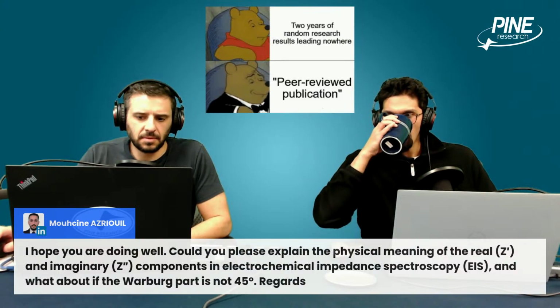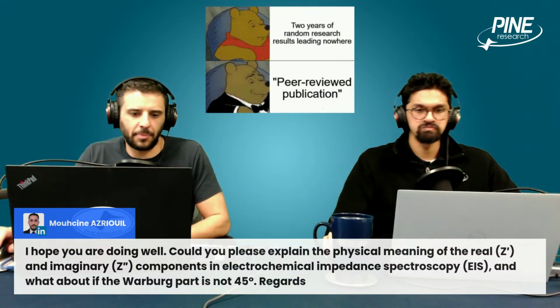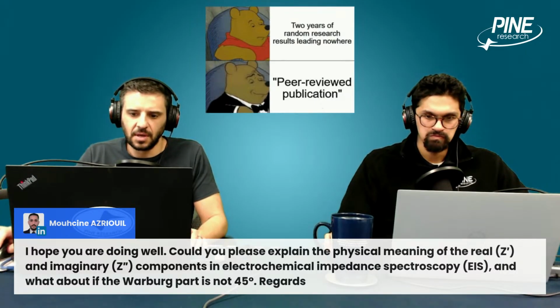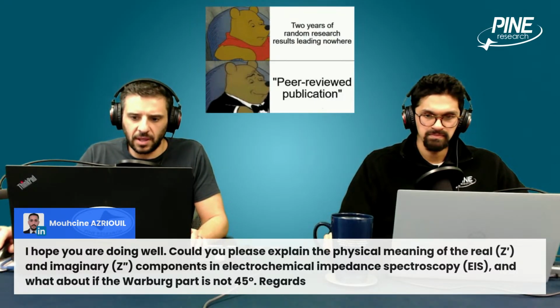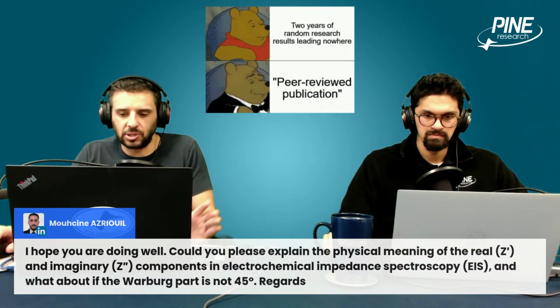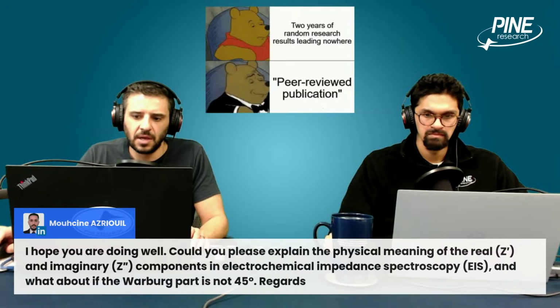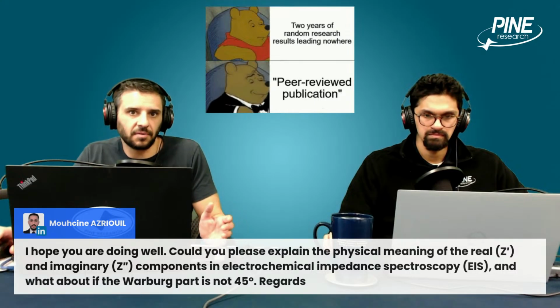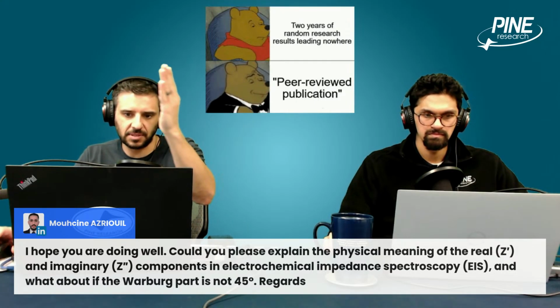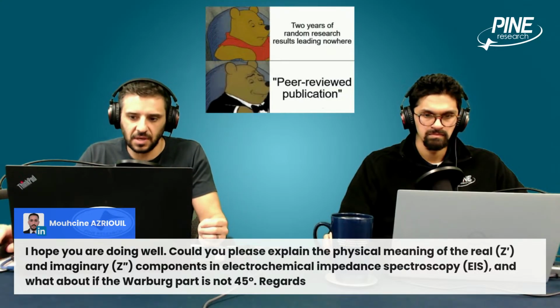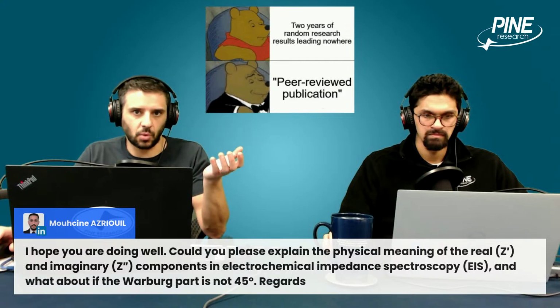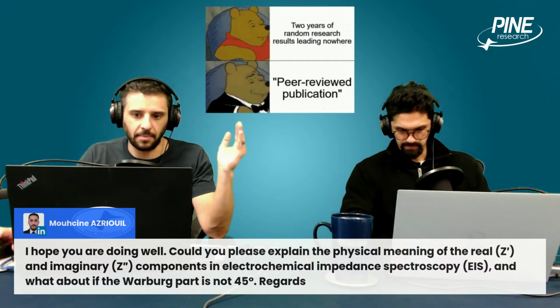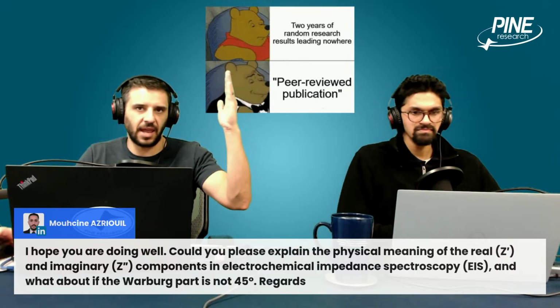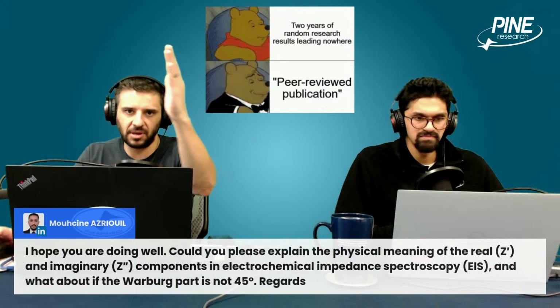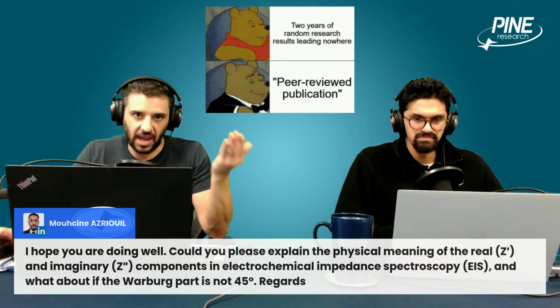Yeah, I think, somewhat more to that point, or just redundancy to a certain extent: one of the things to think about, with your last point about time and the speed at which things are moving, is that a 45-degree angle is diffusion, right? It's like a plane of ions moving at some speed. That's what the diffusion coefficient is in terms of units. It's centimeters squared per second, an area plane per time. So it's an areal speed, sort of. That's the 45-degree angle.